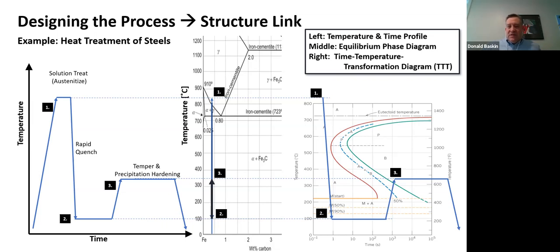As you heat materials, these little particles grow. If they're initially coherent, as they grow to a certain size, they will become incoherent. And as they become incoherent, the material is not as strong as it once had been. So you can over age a material so that it loses strength in a bad way. And I told you the story about how I once was responsible for an aluminum electric motor housing, and